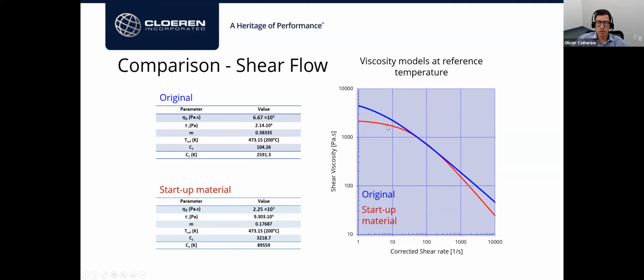The original material, I still don't know exactly how it was made, but the startup material was coming directly from the line and was really a true characteristic of the extrusion process there. Even though it was the same formulation according to the customer, it seems like the process did change something. So the new material that we characterized showed some lower zero shear viscosity and also, quite interestingly, a higher shear thinning effect.